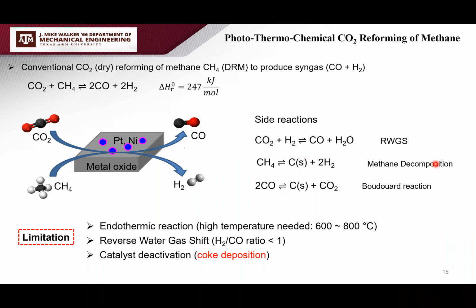And also there's a side reaction like the reverse water gas shift, and also the side reactions of methane decomposition and the Boudouard reaction can cause coke deposition on the surface so that the catalyst deactivates. This is the main reason, deactivation is the main reason that this dry reforming is not commercialized yet as compared to the steam reforming.